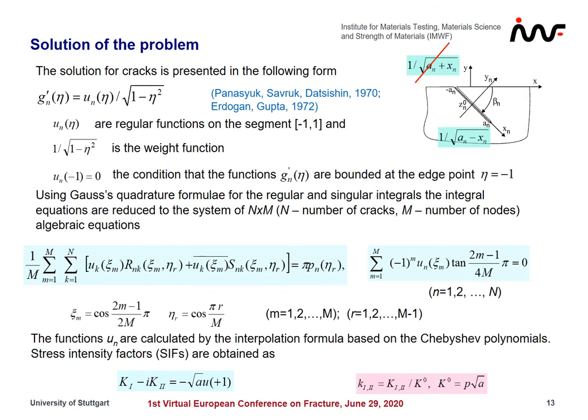The singular integral equations are reduced to a system of algebraic equations. After calculation, the functions are evaluated by an interpolation formula based on Chebyshev polynomials, and then the stress intensity factors are obtained.